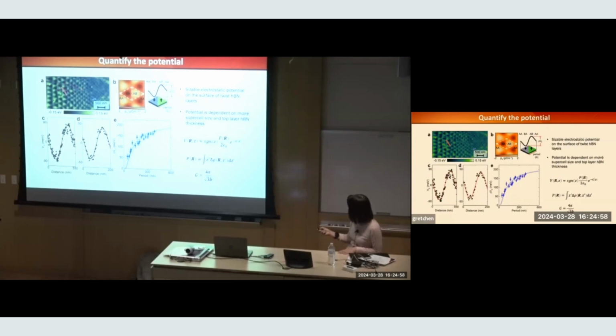People who do transport measurement will be horrified by these spatial gradients. Some are bigger, some are smaller, and they're triangular, not hexagonal, partially because of what's called lattice reconstruction, but I'll spare you that detail, just to say you have these superlattices. Also with this twisted hBN, we have a gradient because there's some built-in strain when we fold them, but it conveniently provides us with an area where we can measure these supercells and measure a size dependence, right? So we're okay with them as a mechanism study.